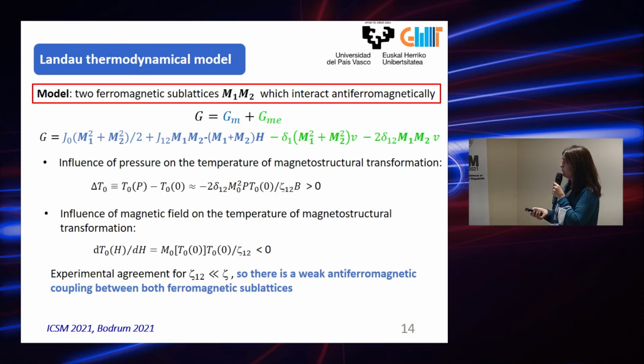With this Landau thermodynamical theory, we can also explain the dependence of this structural transformation temperature on the pressure, depending on this elastic constant, and also on the magnetic field. Okay, this theory and the fit with the experimental results lead us to conclude that there is a weak antiferromagnetic coupling between the two ferromagnetic sublattices with which we can model this system.